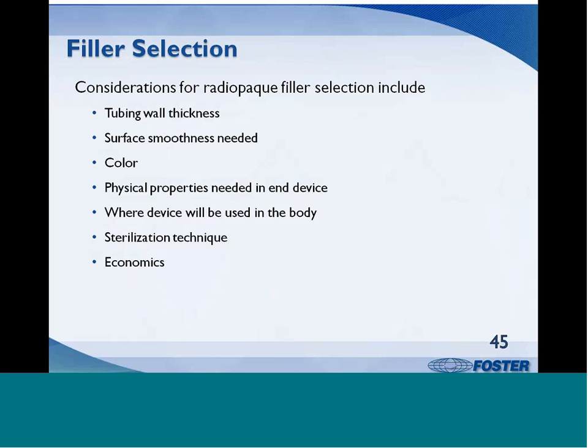Filler selection depends on a series of considerations. As tubing wall thickness decreases, a filler with higher attenuation or higher density is required to see the device. All fillers have different physical shapes. A smooth, platy particle can yield a smoother extrudate than a rough, irregular one. Some fillers, such as tungsten, are very gray and don't lend themselves to coloring. When maximum physical properties are needed, minimum filler loadings are necessary. That requires the highest elemental density.